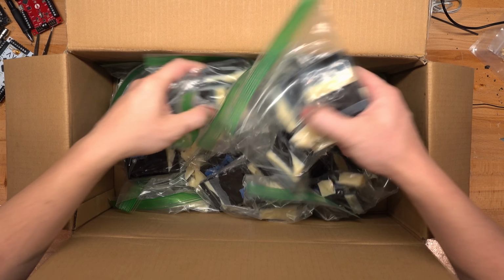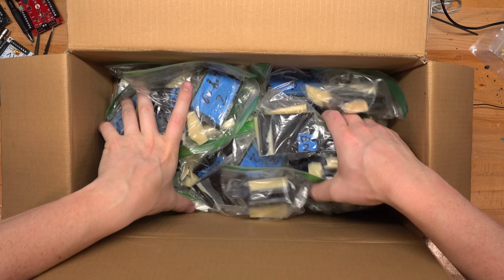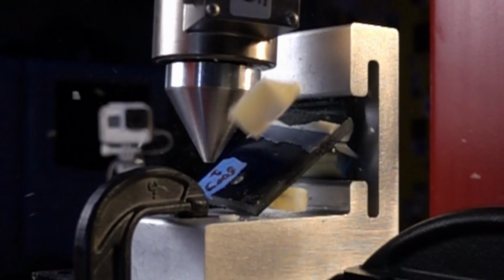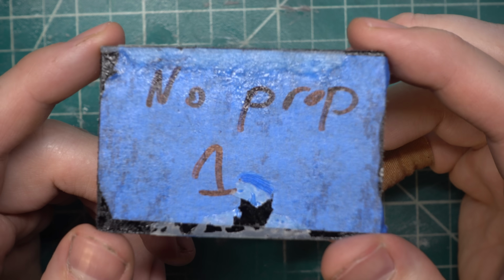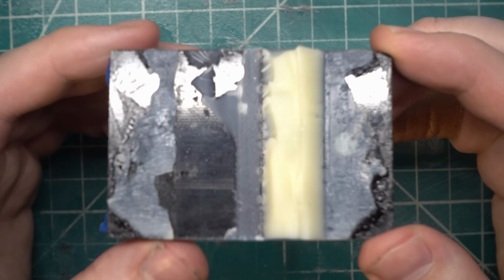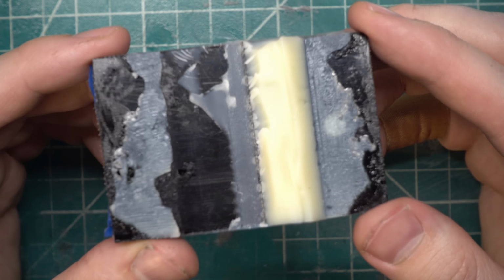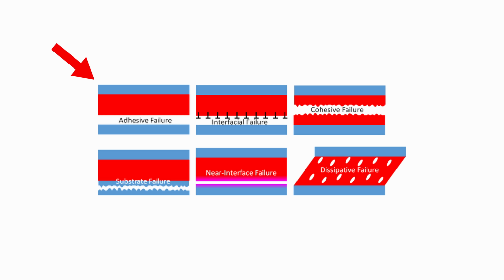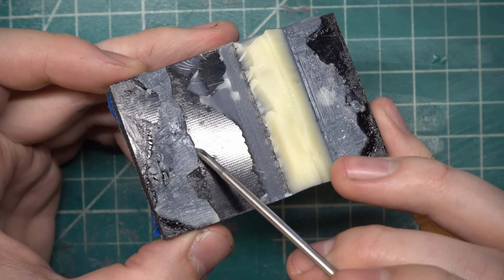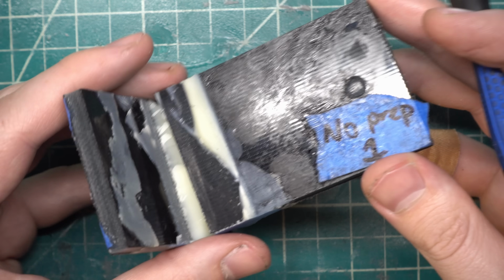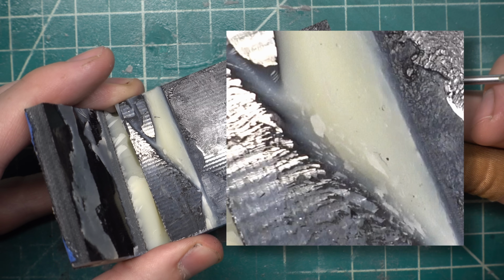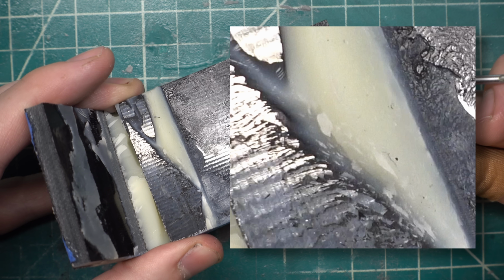I'm keeping each of these samples in bags with their associated shrapnel. I mean, the epoxy shards that come off. For one of the no-prep coupons, it's no surprise these didn't perform well. The glossy surface tells us this is an adhesive failure, i.e. the epoxy delaminated from the surface of the resin in the fiberglass. I do see areas where this isn't the case, which means we probably got lucky on the samples that performed well.